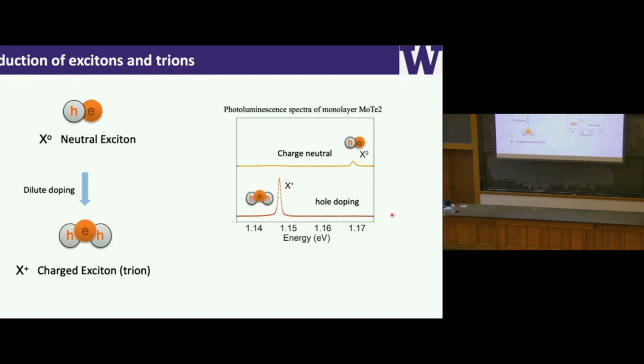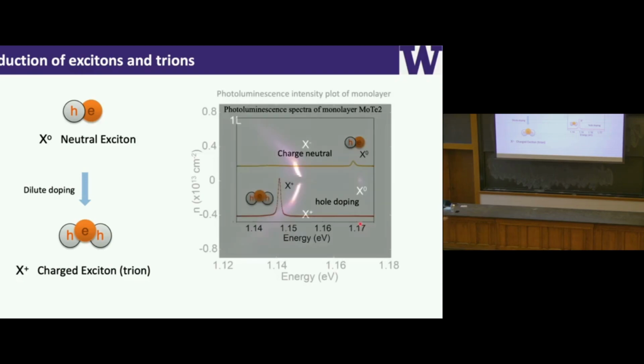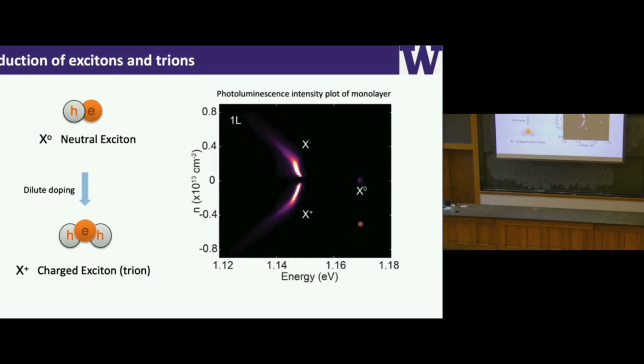So here I show an example of photoluminescence spectra of a monolayer MoTe2. The top spectrum is from the neutral exciton, and the bottom spectrum is from a hole-doped trion state. You can see that the trion state has a 20 meV energy difference compared to the neutral exciton. Okay, so that's how we tell there's a neutral exciton, there's trions.